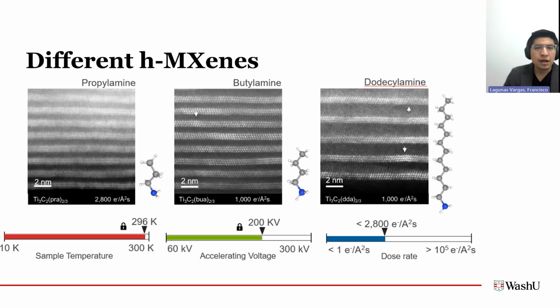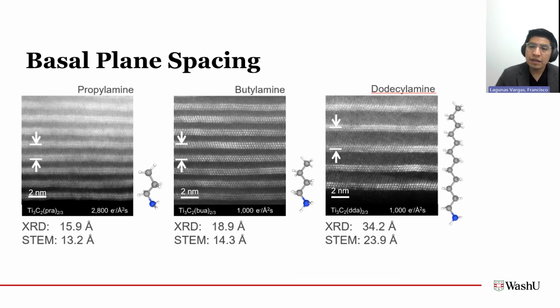So here I show propylamine, butylamine, and dodecylamine MXenes. You can see the organic molecule next to the image itself. And in general, we saw pretty much what we would expect. So the larger the surface group, the larger the spacing between the MXene layers. And with the larger spacing between the MXene layers, we also began to see these slight little bumps or modulations in the spacing between these MXene layers, or the basal plane spacing between these MXenes. So we can go ahead and start getting some statistics about that.